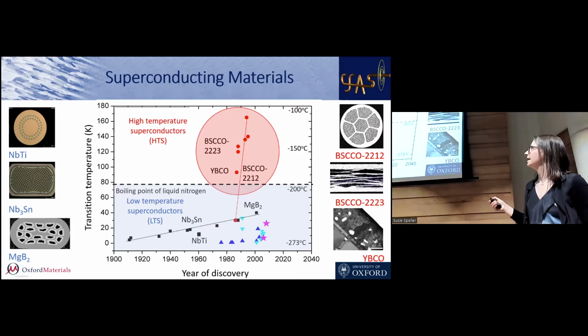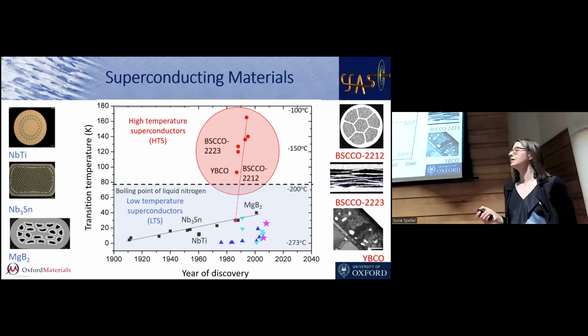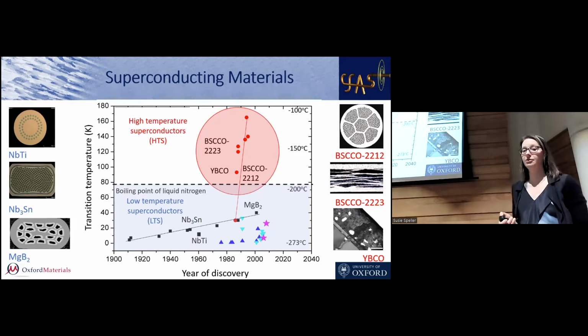So these have got very complicated names, and again, I've only labeled a few of them. YBCO, that's yttrium barium copper oxide. This one, BSCCO, is bismuth strontium calcium copper oxide. And the numbers here refer to how many of each of the elements you've got in the compound. So there are two different BSCCO compounds, 2223 and 2212, which you can both go and buy as commercial tapes. So you can see them over here. They're part of our technological superconductor family. YBCO, or REBCO more generally, you can replace the yttrium with other rare earth elements. You can buy that as well in the form of a tape. And I'm going to talk pretty much exclusively today about this material, which is this YBCO tape called coated conductor.